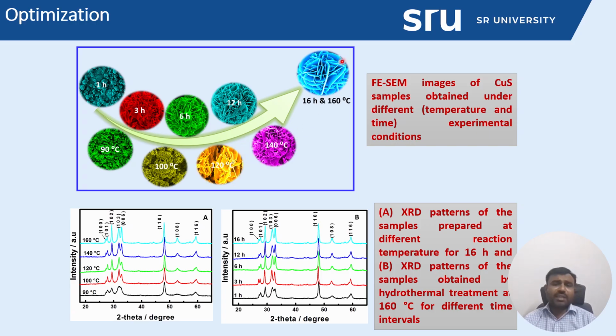Further increasing the temperature to 160 degrees, we can get a fully developed flower-like morphology. When increasing further more than 160, like 180, the morphology does not change. It is similar to the 160 morphology. Hence, for successful formation of copper sulfide, we need a 16-hour reaction time, and 160 degrees is sufficient to obtain highly uniform copper sulfide microflower structures.